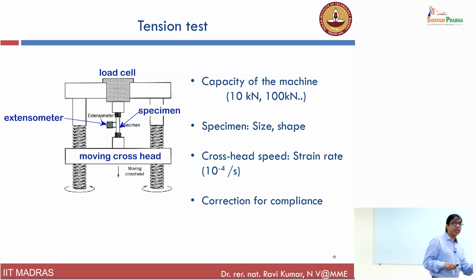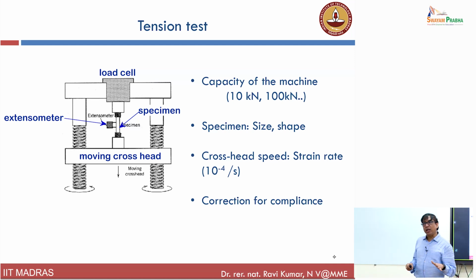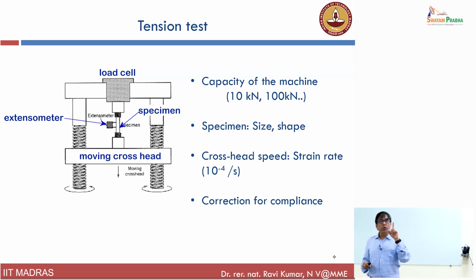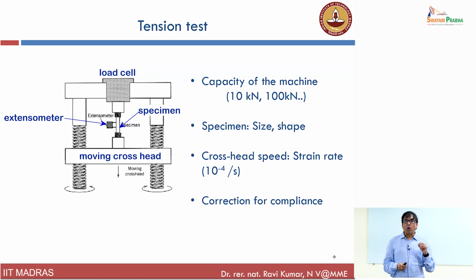So irrespective of tension or compression or bending, whatever testing technique you use, you always have to do compliance correction. Compliance correction is nothing but removal of the instrument contribution to the data that you get from the material. So once you remove that, whatever data that you get is purely because of the material contribution. So compliance correction is very important.